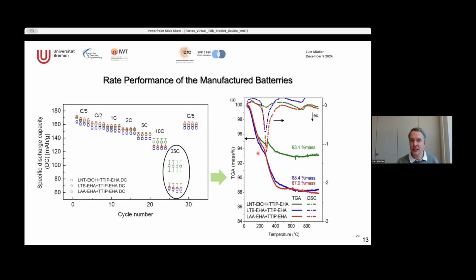But there was a little bit here with the thermogravimetric analysis. There was a little bit of some combustion products we have sometimes in this process, a little bit left compared to the green ones. And this little bit was already shown here. So basically, either you know what you're doing, or you need to pre-treat your powder to really get rid of everything that has been basically absorbed on the surface, and then put it in a battery. But you can also just have a treatment step where you treat them to get surface pure